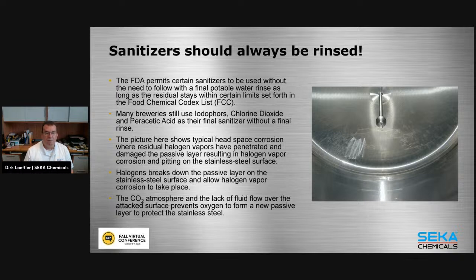And what will happen in the meantime, if you use chlorine dioxide, iodophores, or bleach, is that those chemicals will start to attack your stainless steel. That's because chlorine dioxide generally breaks down into chlorides, and iodophore releases elemental iodine in the vapor phase. So all these things will start to nip away at your tank. And then we find ourselves with no pitting here, but pitting in the headspace, because this was above the water surface.